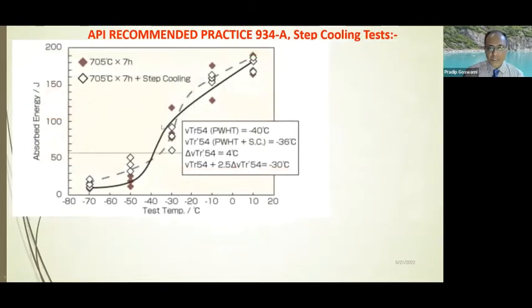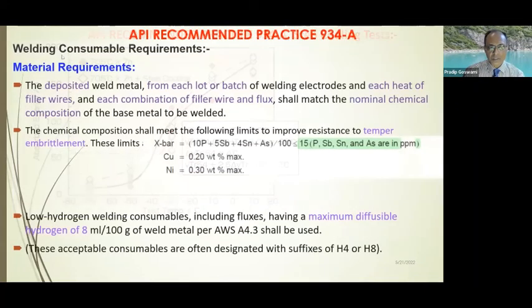As you can see here, this is taken from literature by Kobelco. You can see how the shift in the curve is happening. As you do the step cooling test, there is a gradual shift in the impact values or impact properties. That means it is going down compared to the impact test without any step cooling. These are typical and very specific requirements.